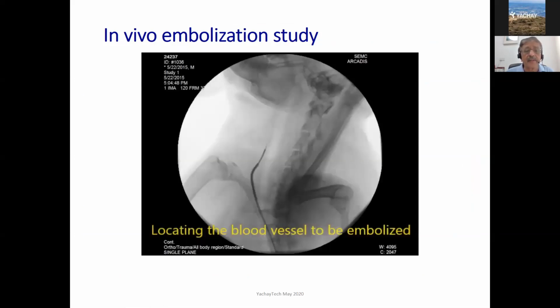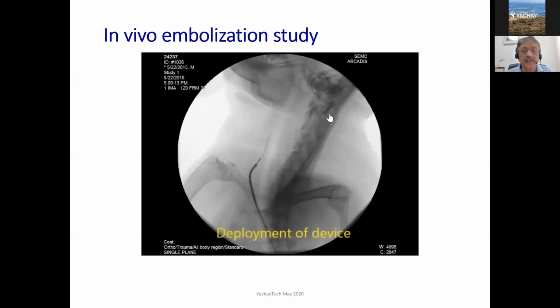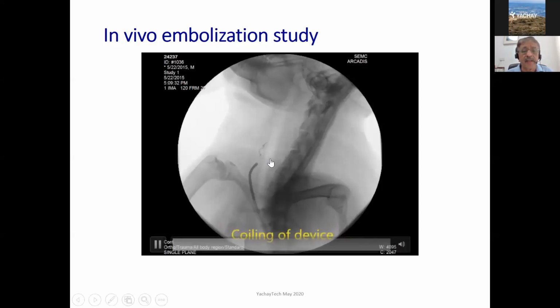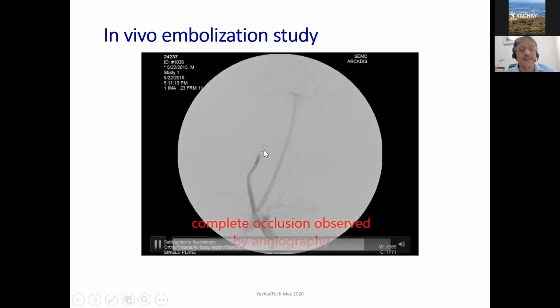First, the blood vessel to be embolized is located by injecting a contrast solution, as you can see here. And then the device is introduced as a rod, and then it starts to coil. And then the vessel is slowly occluded within about 30 or so seconds. Reduction in flow starts to happen fairly quickly, and eventually it's completely blocked, as you can see. Okay, as I hope you can see.